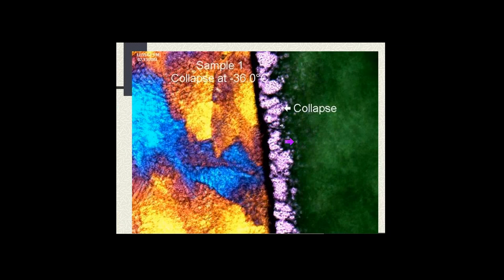This is where we just start to go through the glass transition. Just on the edge of that glass transition, we get, again, what we would call partial collapse. And this may manifest itself in a product as pores opening up in the product, or even the product shrinking away from the side of the vial, you know, shrinking in on itself. And then finally, we hit a temperature, in this particular case negative 36 degrees, where we totally lose the structure.